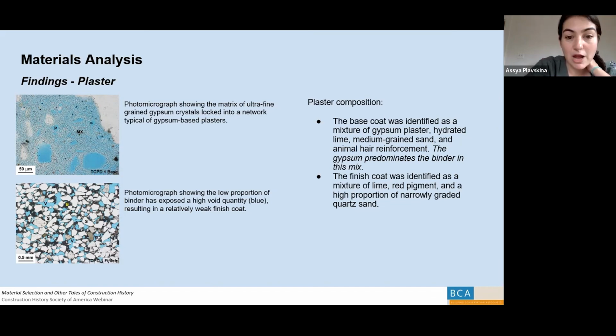The bottom left photograph, that photo micrograph, is an epoxy impregnated sample, which means the epoxy is impregnated into the plaster sample, and the epoxy is blue. So everywhere you see blue in the photograph, that's an area of a void that's been filled by epoxy, and you can see there's quite a bit of voids.